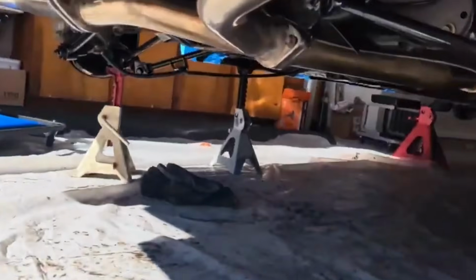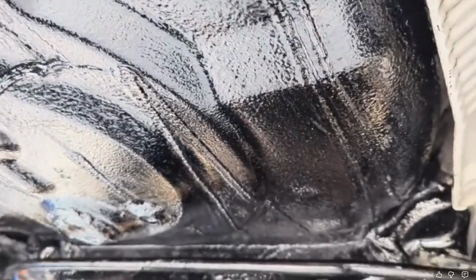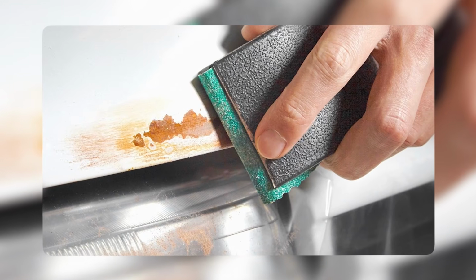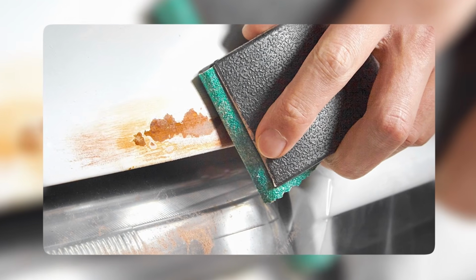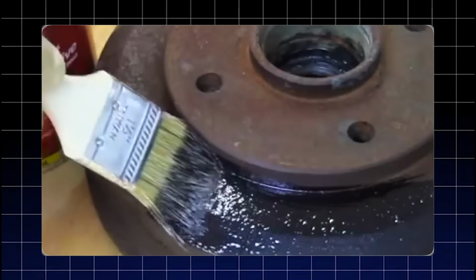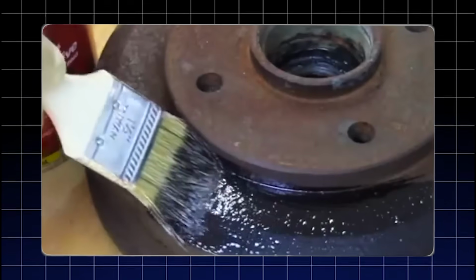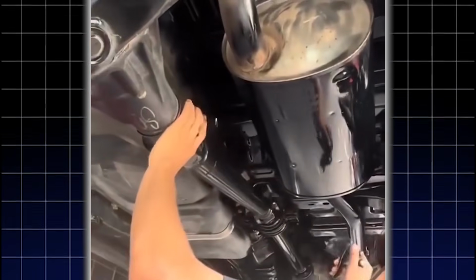The substrate tolerance allows application over mechanically cleaned rust without requiring bare metal preparation. Wire brush removal of loose scale and debris is the required preparation level. Grinding to bare metal, which is the preparation requirement for the most demanding primer systems, is not necessary for Rust Bullet to achieve full performance.